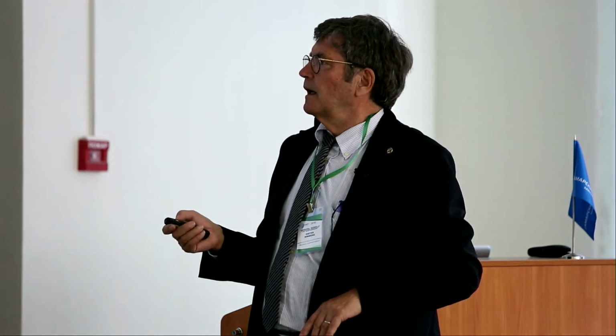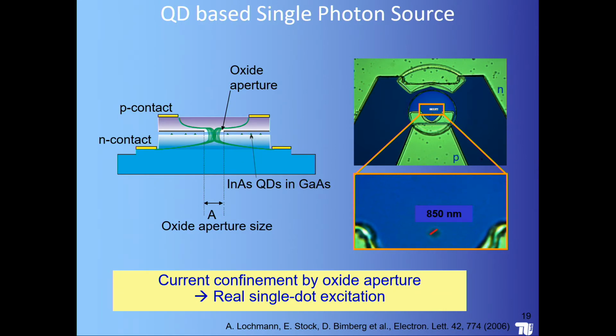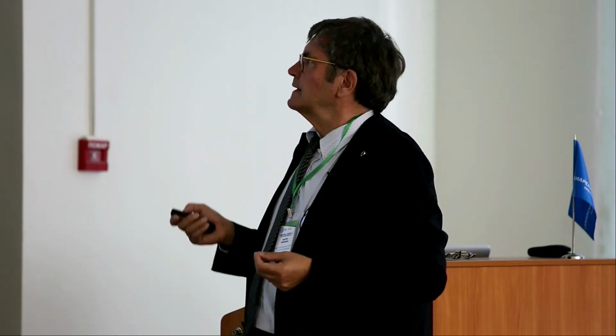You make a layer of very strongly diluted single quantum dots, and then you make a trick which we learned from fabricating surface emitting lasers. We fabricate oxide apertures. What is an oxide aperture? It's aluminum arsenide which is oxidized in water vapor, such that it transforms to aluminum oxide. What is aluminum oxide? Sapphire. A strong insulator. Suddenly you have, instead of a semiconductor, an insulator. The insulator, first of all, channels the current, and second, of course, guides the light.